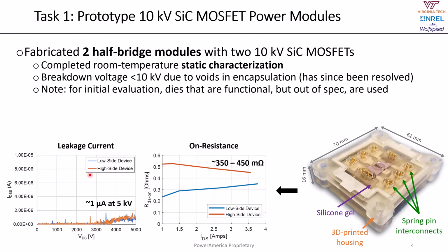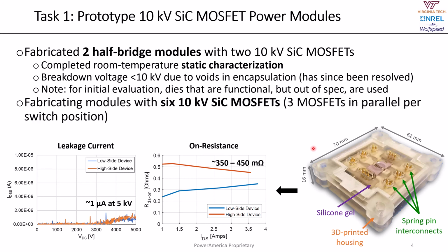In the initial prototype, which was built using dies that are functional but out of spec, we were able to get reasonable on-state resistance and leakage current. However, in the initial prototypes, we had some voiding in the encapsulation. That issue has since been resolved, and so we're looking forward to now moving on and fabricating 10 kV modules with 6 10,000 volt silicon carbide MOSFETs total. That's 3 silicon carbide MOSFETs in parallel per switch position, and this will be done to show the scalability of this type of power module package assembly.